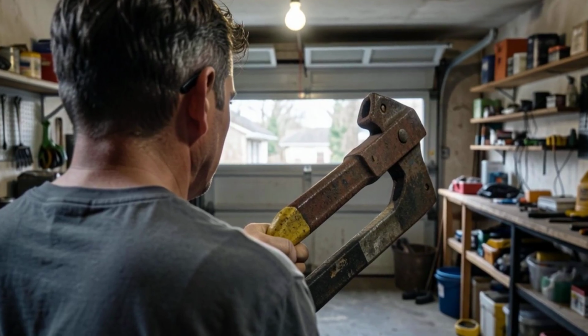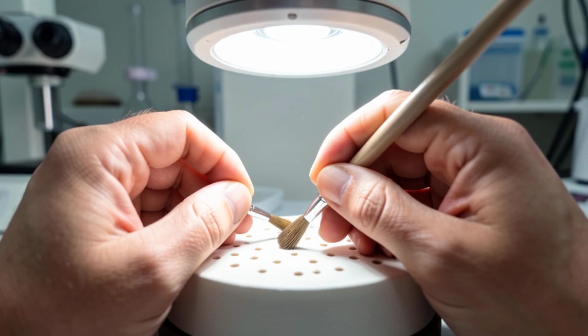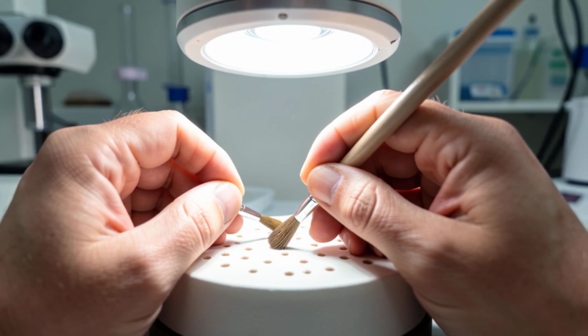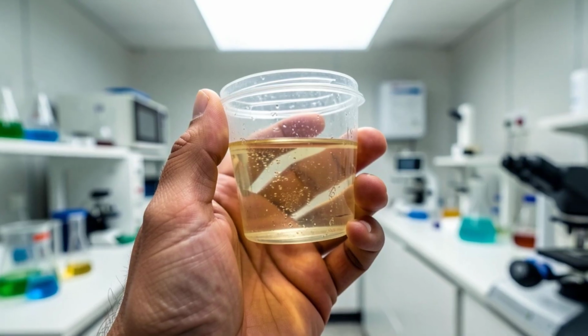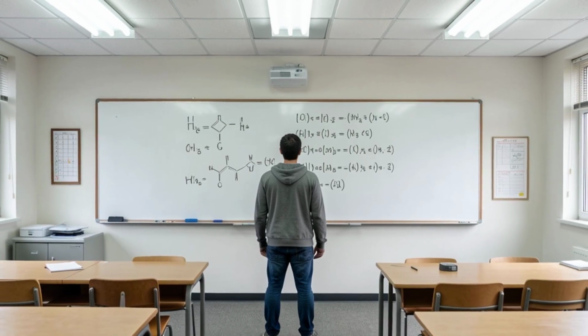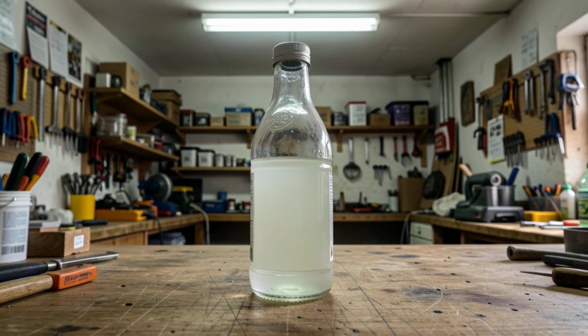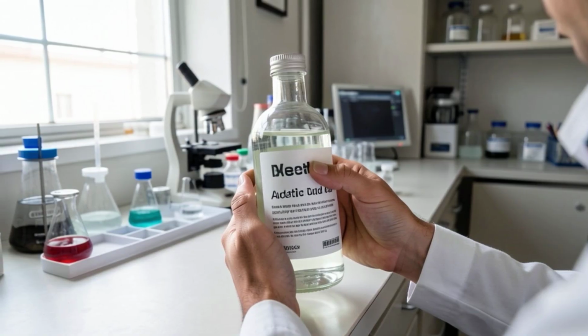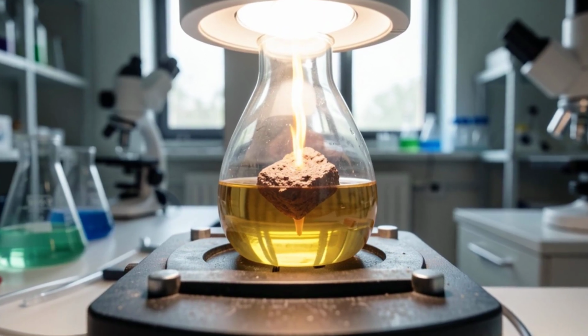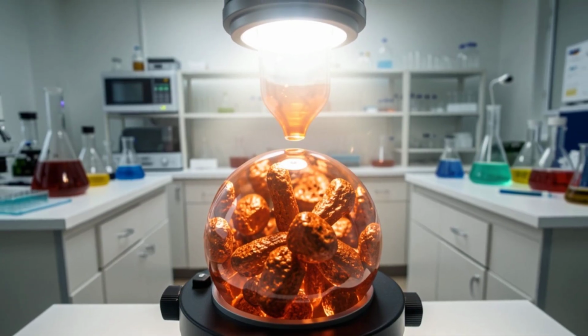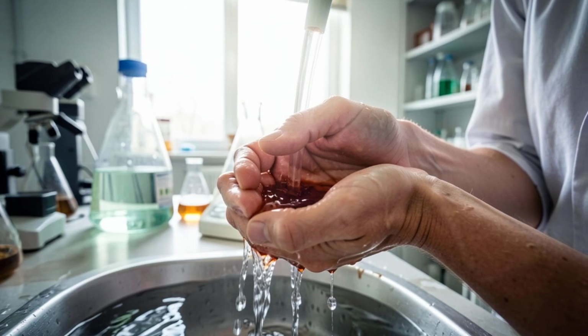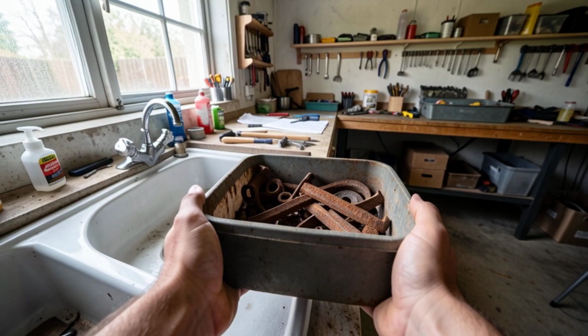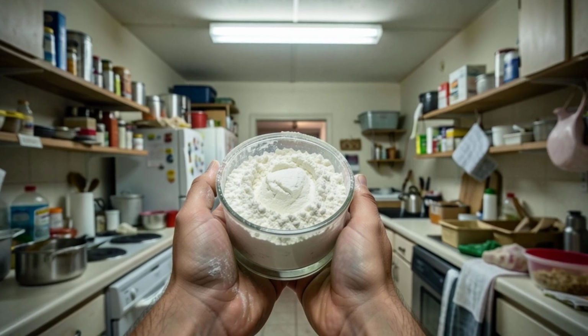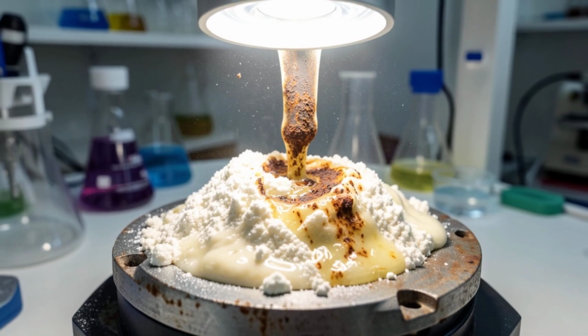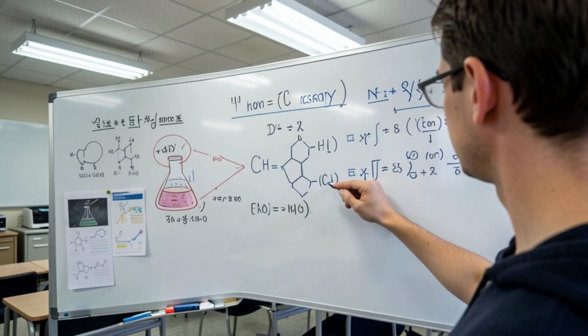So the question was never just, how do we clean the surface? The question is, how do we get into those pores, dissolve what is inside them, and extract the dissolved material out of the metal entirely so it cannot resettle? That is exactly what the potato starch and vinegar combination accomplishes, and here is the chemistry that explains why. White distilled vinegar contains acetic acid, a mild but highly effective organic acid that reacts with iron oxide and converts it into iron acetate, a water-soluble salt that can be rinsed away.